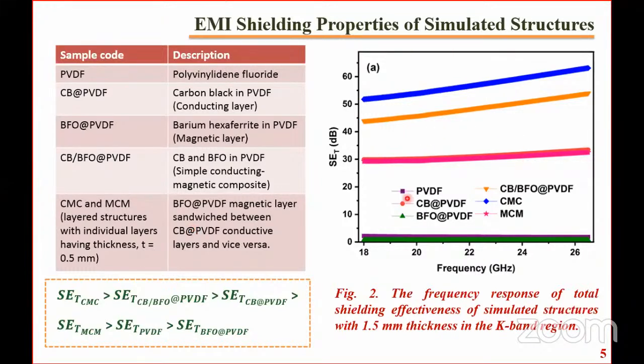From the shielding studies of the simulated materials, it is clear that the CMC layered structure exhibited maximum shielding effectiveness out of the many fabricated materials, that is the PVDF, carbon black PVDF composite, barium hexaferrite PVDF composite, the conducting magnetic carbon black BF simple composite, and the layered structures. This can be attributed to the importance of engineering the material rather than going for a novel material. If you give importance to the engineering of the particular material, it will give better EMI shielding performance.